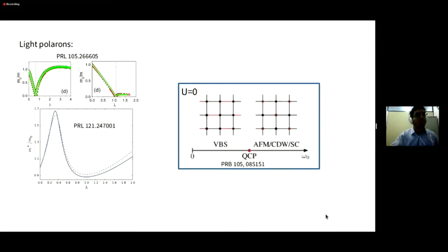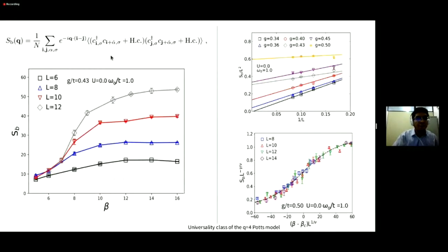Very recently, this model, the SSH plus the Hubbard term, has been investigated by many groups, but they were interested more in zero temperature. My group here, we were interested in the opposite limit, finite temperature, because it's the properties at finite temperatures that can provide the possible occurrence of these light polarons. So this is what we did. We analyzed the SSH model, in particular the bond-bond correlation functions at half filling first of all, to see the formation of this VBS phase, the valence bond solid phase.